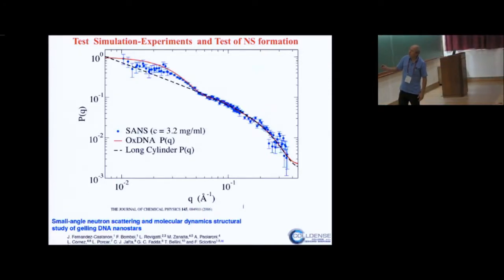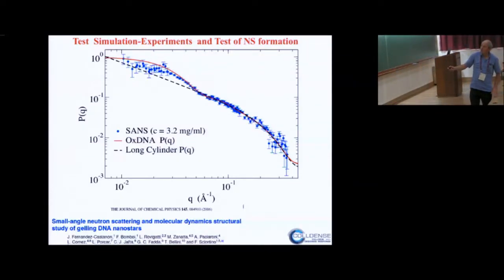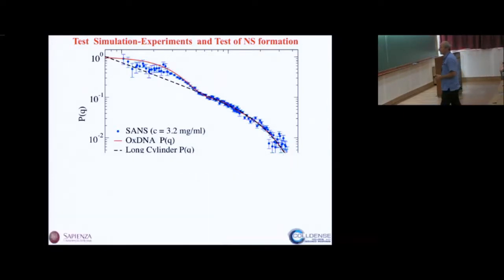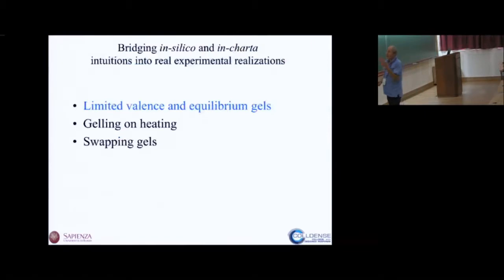In your solution, this is the form factor of the particle that you calculated theoretically, the red one. The blue points are the experimental data. You see how nicely they match. Only at very small vector there are some differences, and they come from the fact that particles are charged, so there is some residual electrostatic interaction. Apart from that, the agreement is very good, and this tells you that you really have a bulk quantity of this material. Okay, now we have them, we can use them.